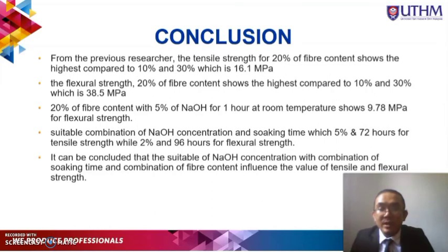20% of fiber content with 5% NaOH for 1 hour at room temperature shows 9.78 MPa for flexural strength. The suitable combination of NaOH concentration and soaking time is 5% and 72 hours for tensile strength, while 2% and 96 hours for flexural strength. So it can be concluded that a suitable NaOH concentration with a combination of soaking time and fiber content influences the value of tensile and flexural strength.